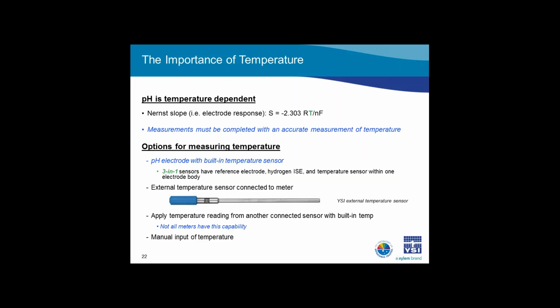Now that you know temperature is important, be sure to periodically check your temperature sensor for accuracy. This can be done by comparing it to a NIST traceable temperature sensor. When comparing two temperature sensors, be sure they are close to each other, preferably with the thermistors touching each other, and the measurements should be within the two sensors' accuracy spec. For example, if one sensor has an accuracy spec of plus or minus 0.2 degrees C, and the other is plus or minus 0.1 degrees C, then the two thermistors should be reading within 0.3 degrees C of each other.